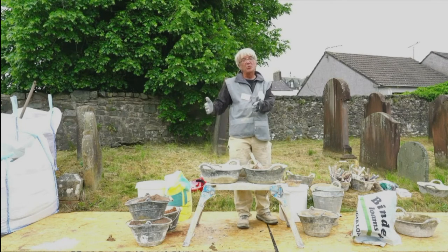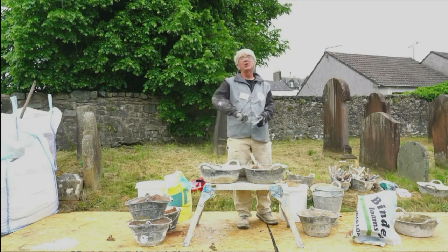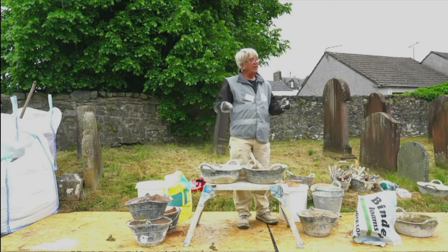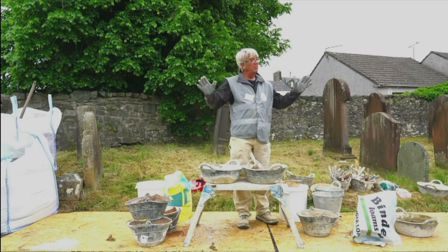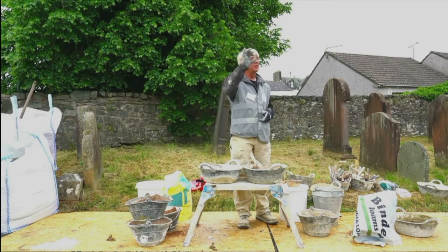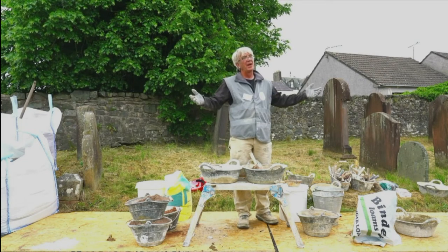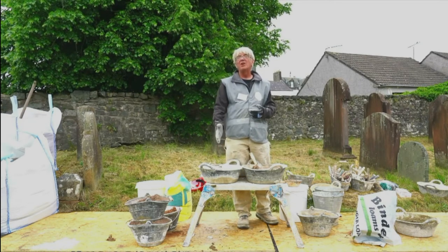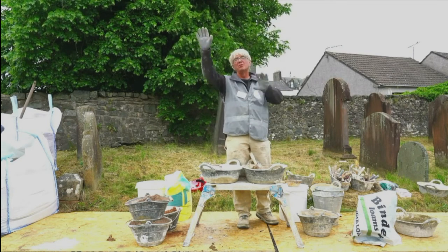And we did the other, we used the Shap 40mm, mixed it there and then on site, put it on stinking hot, and a week later when it had all set up, in all those 8 square metres, we had 2 centimetres of late slaking. And this is a base coat, of course, so what does that matter? Late slaking is really only an issue in your fine finish coat.